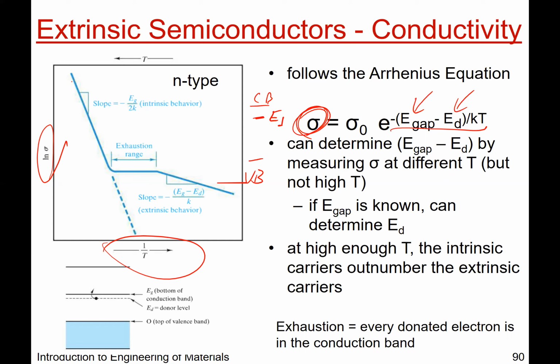But here, there's one mode, and then some range where your conductivity is not changing, and then another mode. So when your slopes are changing, that's an indication of different processes happening in your material. Right? So if it's, say, oxidation or diffusion, what it's telling you is that probably there's a phase transformation or something else happening in your lattice, and thus you have two different slopes. Here, you have two different slopes and also what's called an exhaustion range. So for this type of extrinsic semiconductor, you have some intrinsic behavior type, and then you have extrinsic behavior type. And here, if you're increasing temperature, it doesn't matter. In this range, it's not changing your conductivity whatsoever. One can also call that the saturation as well.